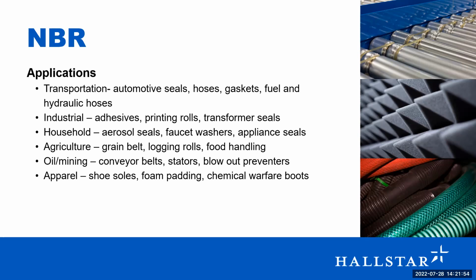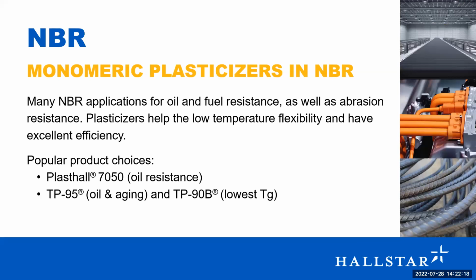A lot of times phthalates are used in this because they do offer a balance of volatility resistance, moisture resistance, and acid chemical stability. But a lot of times there's going to be regulations that are going to be pushing out phthalate chemistry. So while phthalates are used very often in this, they might not be the best plasticizer selection for this elastomer. So like I mentioned, traditionally monomeric plasticizers are going to be used in these sort of applications. They need to have that fuel oil resistance as well as abrasion resistance. Plasticizers really help that low temperature flexibility and have really, really excellent efficiency. So some of our popular product choices we have in this field are Plasthall 7050. That's going to be one of our lower polarity monomeric ester chemistries.